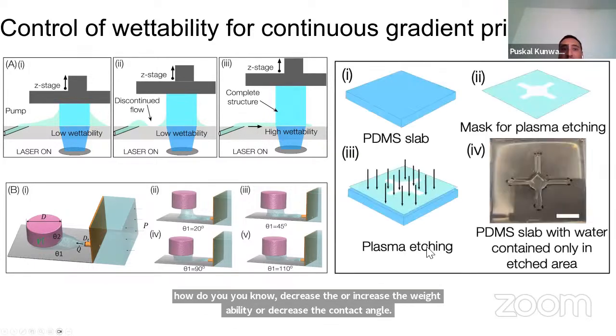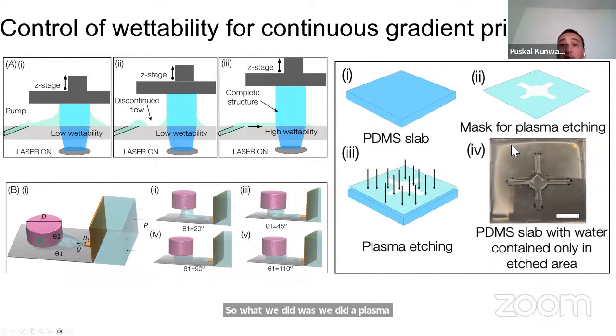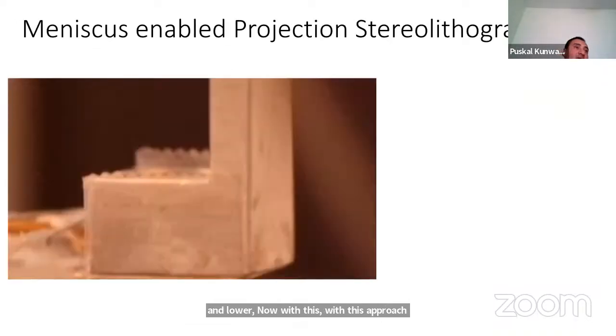What we did was plasma etching. Basically, the plasma etching process decreases the contact angle and increases the wettability. For example, we made a cross pattern structure and plasma etched it. This is just a slab, and there's a pattern where this is a hydrophilic area and this is a hydrophobic area. Water will stay only in the hydrophilic area, so that way you can distinguish higher and lower wettability areas. With this approach, we etched the higher wettability areas and did a gradient PSLA, and let's see how this works.